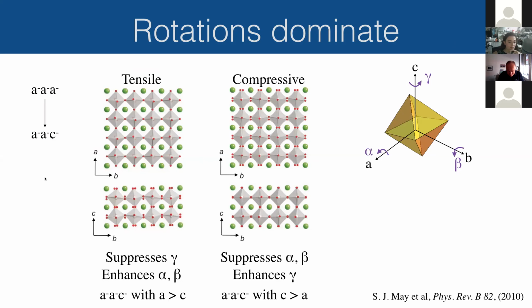So rotations dominate. This is a really nice study that was done with lanthanum nickelate thin films on 2 different substrates, one that gives a tensile strain and one that gives a compressive strain. Lanthanum nickelate in bulk has a Glazer notation that is A-, A-, A-. So it has out of phase rotations around all 3 axes of the same magnitude. When you make it into a thin film, because of the biaxial strain, you're breaking symmetry between the in-plane and the out-of-plane direction. So unsurprisingly, what you end up with is A-, A-, C-. So now this rotation has a different magnitude to the other 2. In particular, on tensile strain, C becomes smaller than A. So it means that you have almost suppressed the rotation around the C-axis by the tensile strain, and you actually increase the rotations around the other axes.